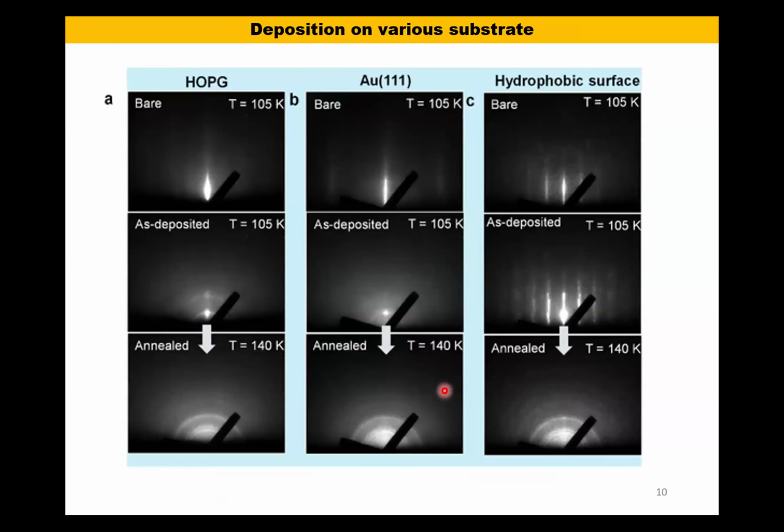Yes. You can see this figure, HOPG at 105 Kelvin. This is crystalline THF buried in the amorphous solid water. I was talking just a second before about why we are facing this. You see, the D-spacing of the pure THF crystalline solid is exactly matching with the cubic ice spacing.